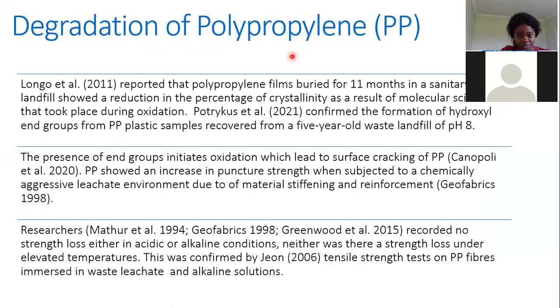Polypropylene degrades by the action of oxidation. Oxidation is a process in which a polymer reacts with molecular oxygen. This oxygen permeates the amorphous region of the polymer, and then oxidation takes place both at the surface and within the polymer. Now, polypropylene is a semi-crystalline polymer. That is, it has the crystalline region and the amorphous region.